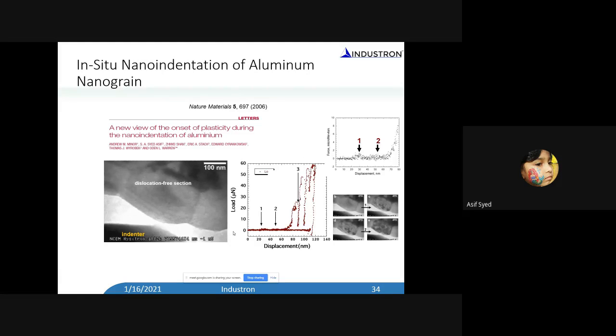Another thing, there was a lot of ambiguity in understanding. For example, when you do indentation experiments, sometimes you see a jump in the load-displacement curve, and these jumps are attributed to sudden nucleation of dislocations. For example, you have a defect-free surface. When you do it at a nanometer length scale, you're talking about statistics. Beneath the indenter, the number of dislocations may be very small, and by applying the stress, you may be nucleating more dislocations. And as the dislocations multiply, you see a sudden jump. That is what has been proposed.